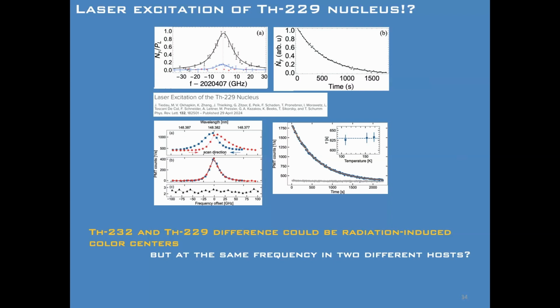And so these crystals are chemically pretty different because that radioactivity has just been sitting there doing stuff to the crystal, right? But the fact that you see it at the same frequency in both LiSAF and calcium fluoride, two different hosts, any color centers you create, they can't get the same frequency. And also that they're so narrow. I mean, it's hard to get a color center this narrow. Our stuff is at room temperature. Means that you can finally say, this is, I think, the nuclear transition.